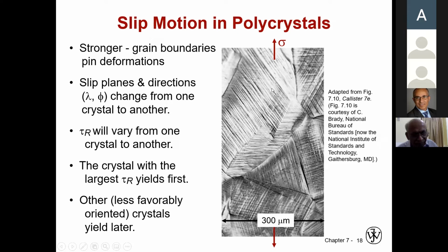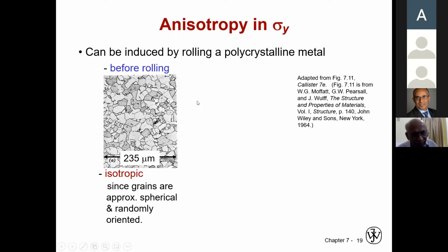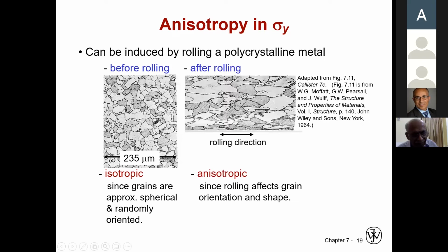When you apply shear, the layers will move with respect to each other. But of course, they will also try to cross over these grain boundaries, which makes it difficult to move. As a result, having more grain boundaries makes it more difficult for the dislocation to move. As a result, yield stress will be higher. So a material with smaller grains will have a bigger yield stress. And of course, we can have anisotropy in different directions, with different yield stresses. But we can introduce anisotropy by loading the system. Like after rolling it, grains change their shape, and now their yield stress will be different in each direction.